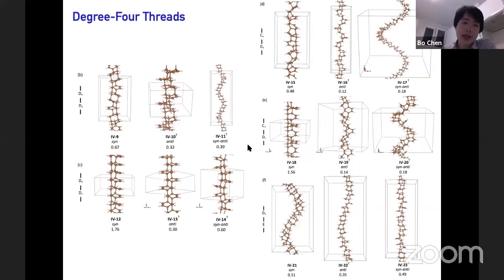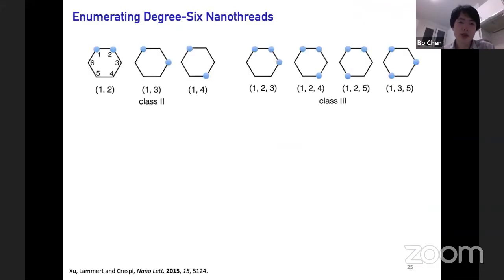Here are some relaxed degree 4 threads. Here you can really appreciate the variety of the structures. We have some very straight ones, some very helical ones with very large unit cells. In total, we have 23, and only 7 of them have this syn configuration that can go on to degree 6 nanothreads. The enumeration of degree 6 nanothreads was done by our collaborator.